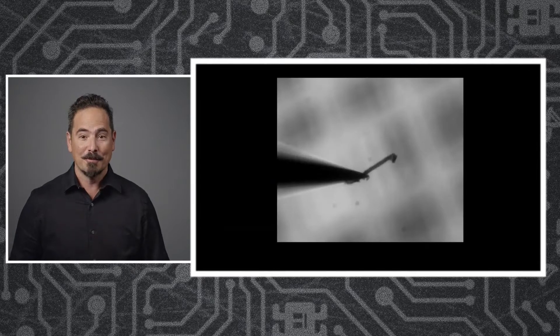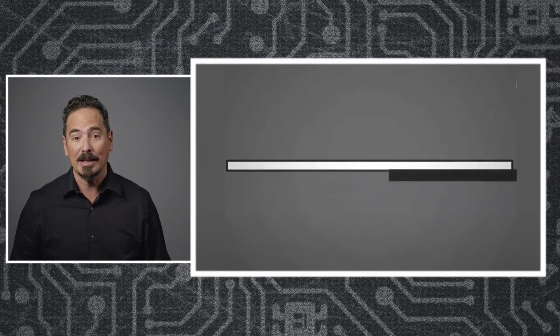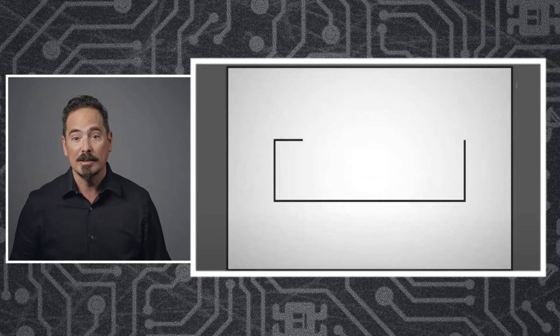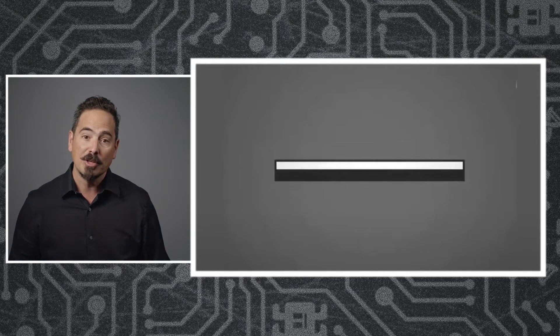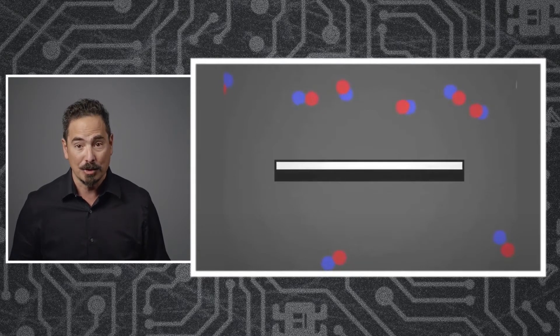How does it work? We start with a 7 nanometer thin platinum layer. We coat one side of the platinum with an inert material like titanium dioxide. We then fabricate the device that we want, and when we put it in solution and put a voltage on the platinum, we can get ions that are dissociated in the solvent to adsorb onto the platinum surface.